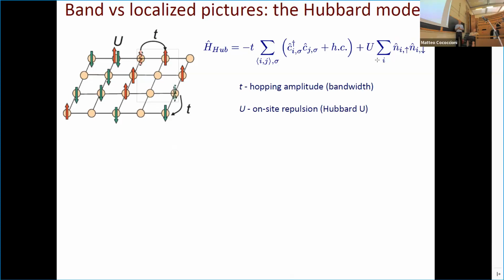So the way we correct this with the Hubbard correction is by introducing a corrective functional inspired by the Hubbard model. As many of you probably know, the Hubbard model is very simple in that it contains only two parameters in its simplest version. That is the hopping parameter T, which is basically the bandwidth that we have in our system, and the electron-electron interaction U, limited to being different from zero only when the two electrons are on the same site. Now, despite its simplicity, this Hamiltonian is flexible enough to capture localization of electrons when the electron-electron interaction is strong enough.